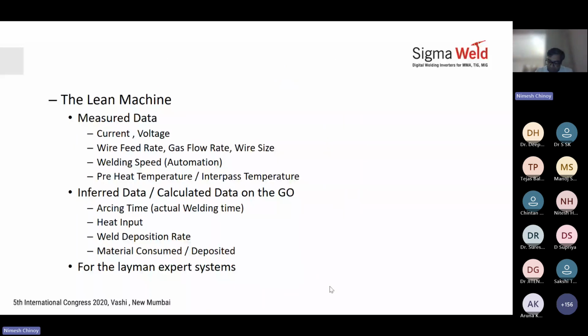What is a lean machine, or what is something that is possible very quickly, is that you can measure the data. What is the welder welding at? What was the current he was welding at? What was the voltage he was welding at? You can measure the wire feed rate in terms of MIG welding or cold wire feeders in TIG welding. You can measure the gas flow rates. What was the gas flow available at that time? You can measure the wire size, whether he was welding with 1.2, 0.8, 1.6. And what was the welding speed, the rate of welding?